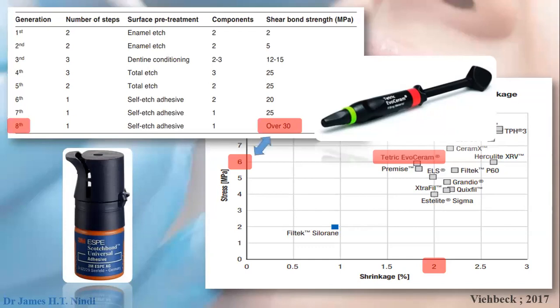Now, if you look at this, if you use an adhesive which has a shear bond strength of over 30, yet the composite that you've used generates a stress of 6 megapascals, it means that the adhesive will be strong. For this to be clear, let's say you've used a first generation, which I don't think is on the market now. If you use a first generation adhesive system, it will offer you a shear bond strength of only 2 megapascals. And if you go on to use this Tetric EvoCeram, which generates a stress of 6 megapascals, it means that when this composite cures, this composite then shrinks, it will generate a stress of 6 megapascals, which is more than the adhesive that you have used of 2 megapascals.